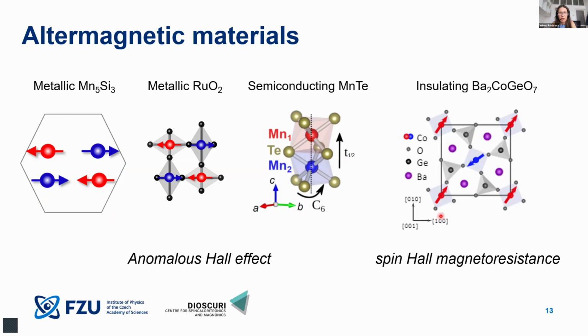And then there is a large family of materials which are even more complicated. For example, a material which is prepared in Dresden at the Leibniz Institute. And you see that here the spins are surrounded by canted octahedra with respect to each other. It's maybe not easy to see at first look, but these relatively complicated compounds very often actually help us to be altermagnetic, because they have some sort of breaking of the symmetries, so that these two spins experience a different crystal environment.